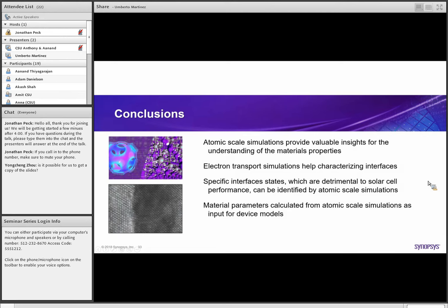Because now that you know the atomic scale processes that occur, you can think about how to increase performance. For example, in the case that I showed before, you can try to passivate these dangling bonds at the interface. Another key point, which we apply on a daily basis for device simulations in the semiconductor industries, and which can be done in the last example I showed, is that you can use this as an input for other types of device models, where you cannot use the bulk material properties.